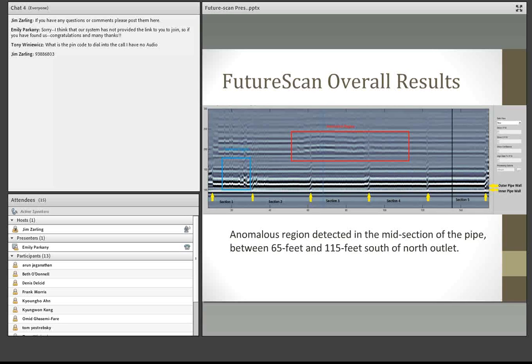And the interesting part about this is that not only did the folks from CUSE use FutureScan to scan for our target voids, but they went ahead and scanned the entire length of the pipe, so it was a full 180 feet. And as they were doing this, not only did they find the targets, which you can see in this upper radargram figure inside that blue box, that's where they found our targets. But they also found this very large, what they called anomalous region, where they suspected that there were also some voids occurring. That's that very large red box you see.